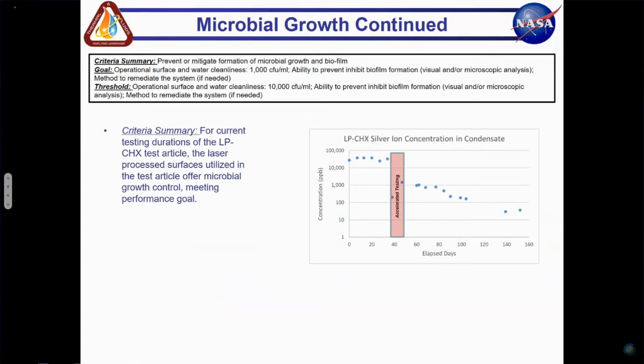Our criteria summary and goal for this was to prevent or mitigate formation of microbial growth and biofilm. Our goal was to keep surfaces and water cleanliness below 10 to the 3 CFUs per mil. The threshold was 10 to the 4 CFUs per mil. And we were able to do that, and we think that's primarily attributed to the silver ion concentration in that condensate. And so that's why I put up the chart here again. We have pretty high levels of silver ions in the condensate. And so we think that the silver ions definitely help. There may also be part of the surface geometry of our condensing surfaces that may also help prohibit microbial growth and biofilm.